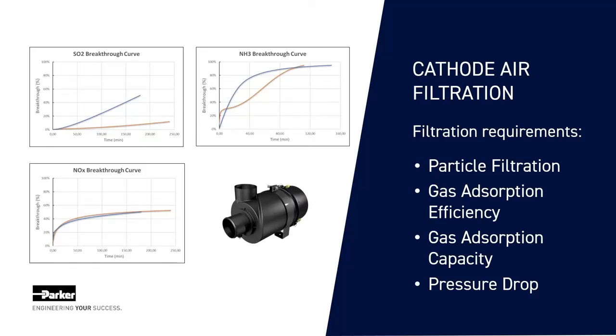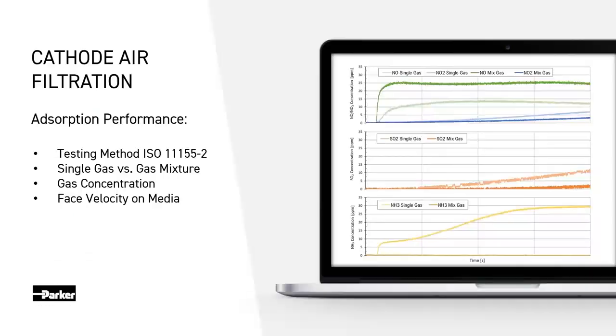There are several types of medias and filtration technologies that can be utilized for the gas adsorption function. As you can see on these graphs here, there are different technologies which will have different performances depending on the gases. So we need to make sure that the correct media and the correct technology is selected in the development of such filters, and this needs to be selected based on the application requirements. The gas adsorption performance is the most important of the cathode air filter. This performance can be tested according to some standardized testing methods, such as the ISO 11155-2. This basically measures the gas adsorption efficiency and capacity of the filters, but the test is conducted on single gases. There are several other parameters which will impact the performance of the filter.